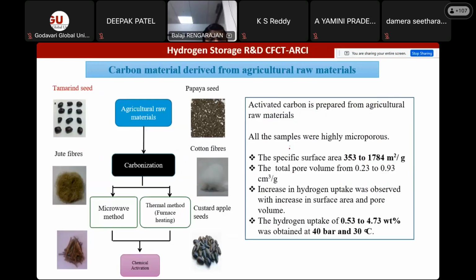So in this context, ARCI has also developed some carbon-based material. Basically, if we take seeds like papaya seeds and tamarind seeds, which have high cellulose content, and do the carbonization, you will get a highly porous carbon, with a high surface area. The main challenge in this kind of physisorption carbon-based material storage is that you have to accommodate hydrogen up to a maximum of 6%.